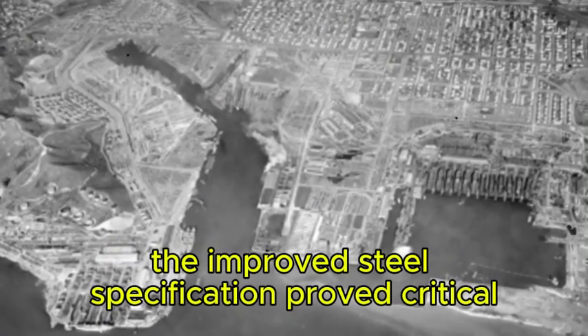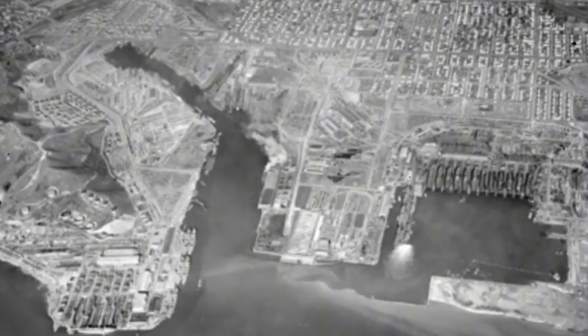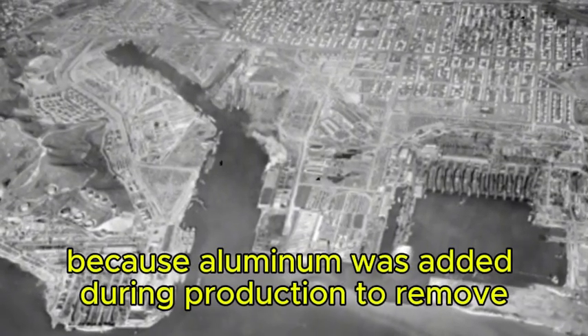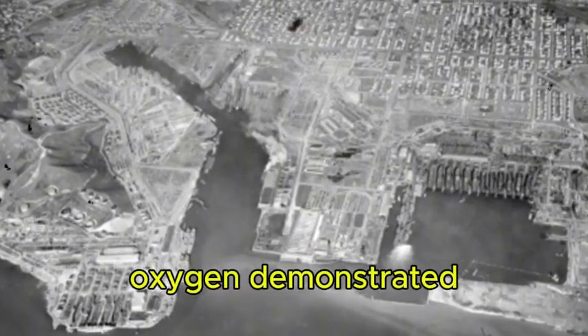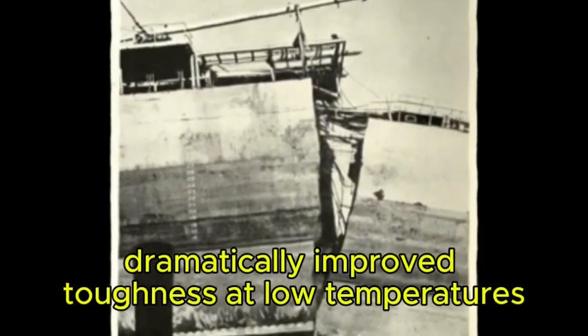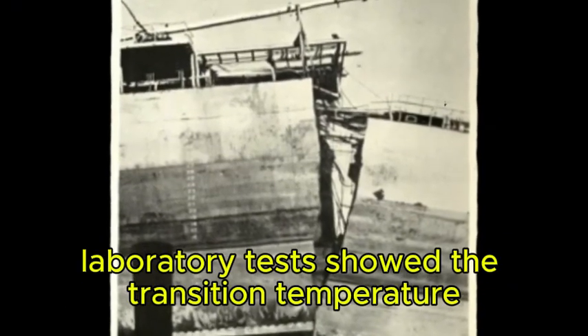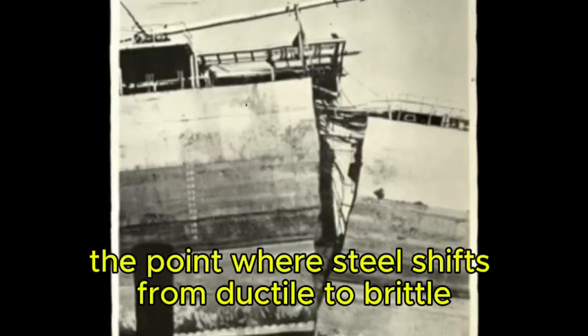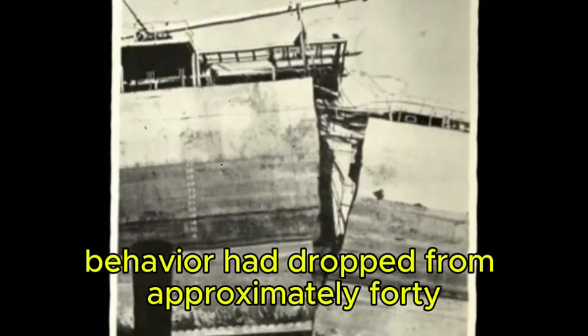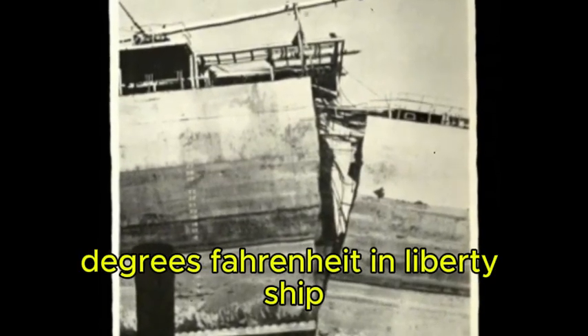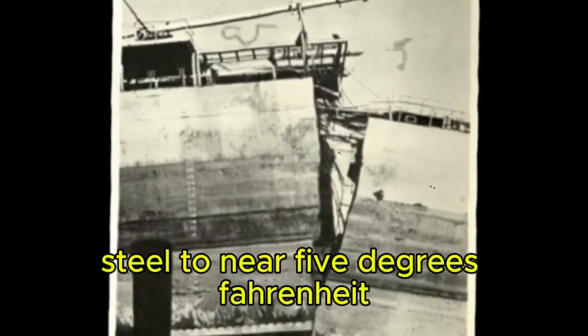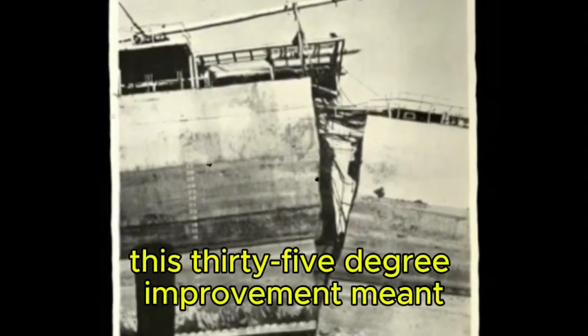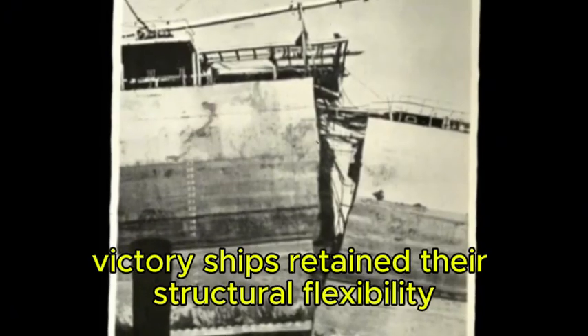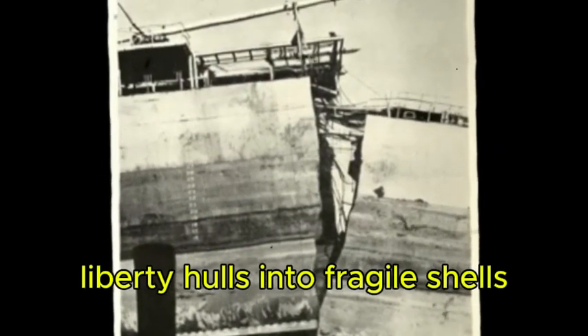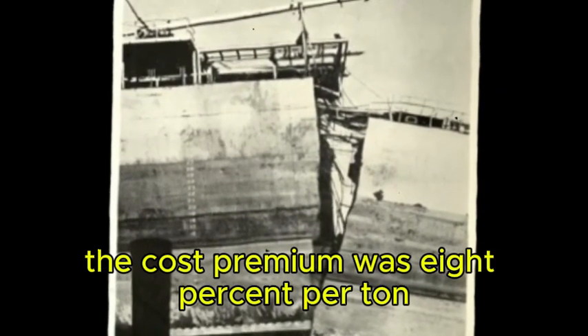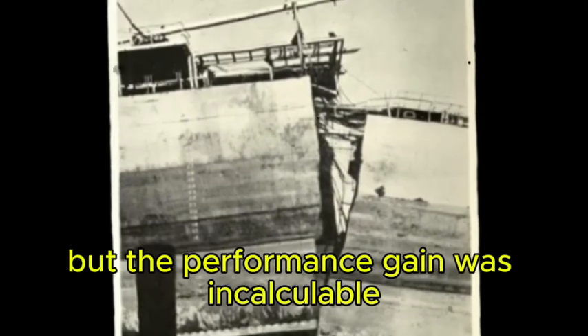The improved steel specification proved critical. The new alloy, designated as killed steel because aluminum was added during production to remove oxygen, demonstrated dramatically improved toughness at low temperatures. Laboratory tests showed the transition temperature, the point where steel shifts from ductile to brittle behavior, had dropped from approximately 40 degrees Fahrenheit in Liberty ship steel to near 5 degrees. This 35-degree improvement meant Victory ships retained their structural flexibility in conditions that turned Liberty hulls into fragile shells. The cost premium was 8% per ton, but the performance gain was incalculable.